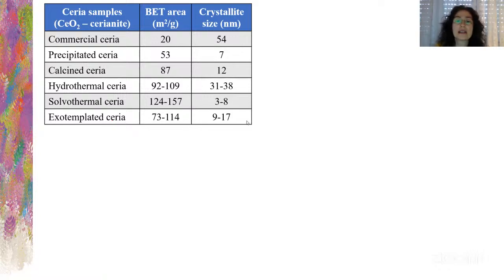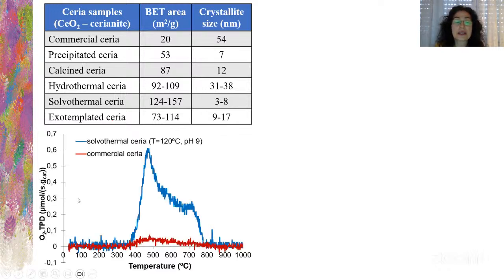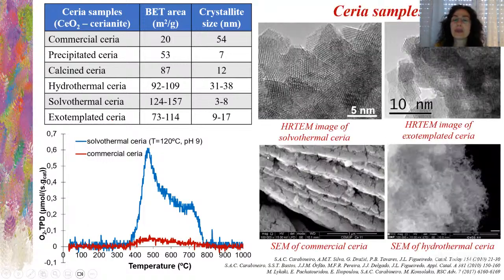Also, we can compare the crystallite sizes here, and that's interesting. Here we have a temperature programmed desorption of the oxygen adsorbed. So here, if we compare the commercial ceria, there is almost no oxygen desorbed, you see here. And if we compare the solvothermal series, you see it has a much higher peak of oxygen. So that is the difference between these samples, which makes them more reactive, as we will see.